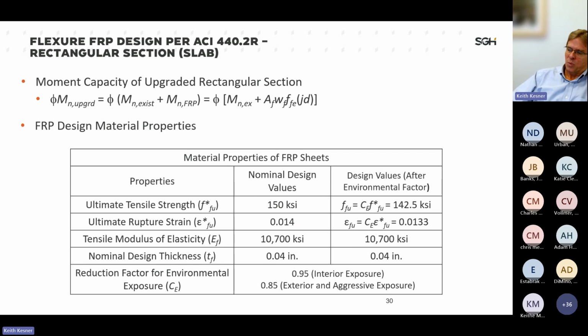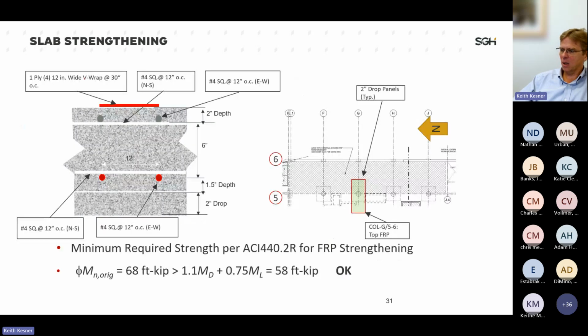This example is doing FRP sheets, so fiber sheets, and with those sheets, we're thinking about both the rupture strain and the tensile strength of the fibers, and then figuring out what the effective strain would be when we're actually applying them to the structure. So we're reducing the nominal design strength to create an effective strength, considering the environmental exposure and the effective strain prior to failure. So what does that look like?